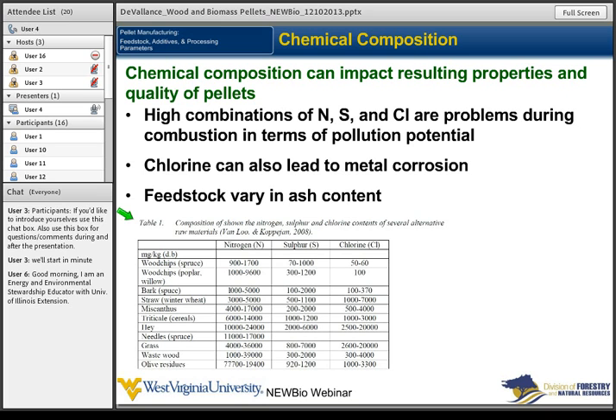We had done some research between yellow poplar and red oak in terms of pelleting, and they had similar surface properties, but when we made the yellow poplar pellets, they had a much lower strength. So other things factor into pellet properties other than just these chemical compositions. But if we start looking at some of these compositions, say poplar, you can get an idea of how much chlorine is in poplar and willow wood chips and spruce versus something like grasses or miscanthus. You can get a lot higher chlorine level if you're pelletizing a miscanthus or grass type material versus something that comes from a wood product. The same thing follows with the sulfur content and nitrogen content.